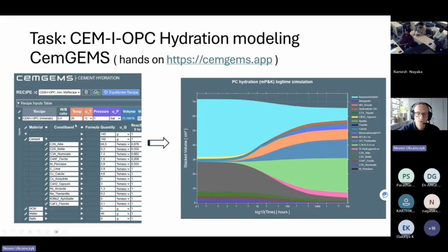So you should do experiments, for example with calorimetry, and then change the kinetic equations in GEMS. That's this kinetic reaction, we will do it tomorrow. There are parameters for these empirical kinetics, and you can increase those kinetic constants, and in that way you can model the filler effect.